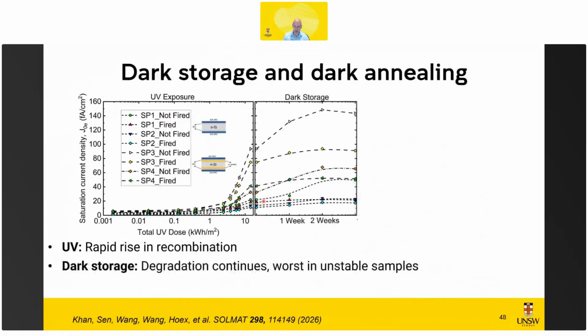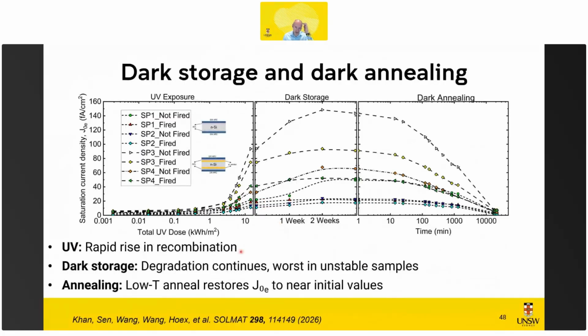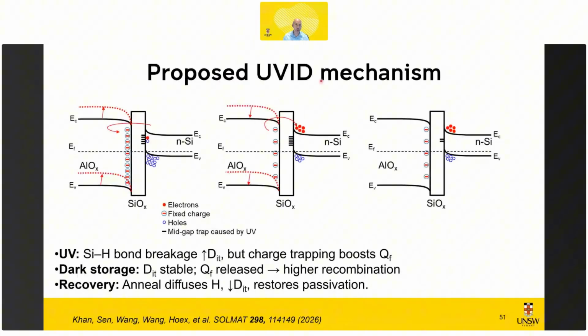This is also a repetition from last time, but it's good to show it again. When we expose to UV, we see this rapid increase. The worst performing samples keep degrading in the dark, and then there is dark annealing. This dark annealing was done at 85 degrees, which is not that high in the grand scheme of things. You can fully recover if you anneal long enough. This allowed us to come to the model that we also presented last time, so I go a little bit quicker.